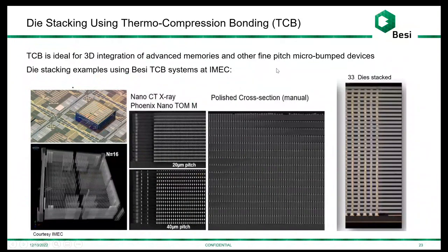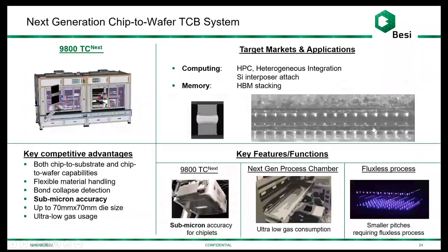One of the technologies that helps us is TCB, thermocompression bonding. This is really helpful for very fine pitch, but not quite as fine pitch as hybrid. So I'm talking in the 20 to 40 micron range. This is an example of very high density memory stacking using thermocompression bonding.